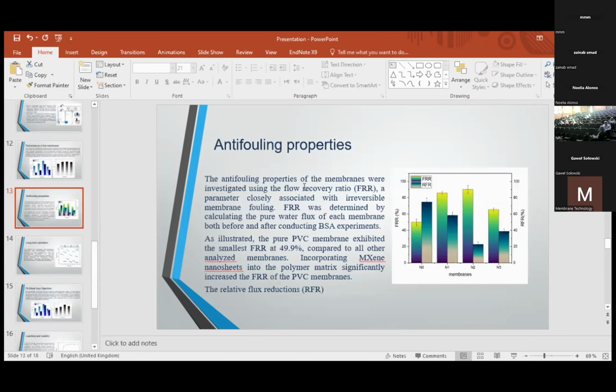For the anti-fouling properties of the membrane, we investigated using the flux recovery ratio, a parameter closely associated with the irreversible membrane fouling. FRR was determined by calculating the pure water flux of each membrane both before and after conducting BSA experiments. As illustrated, the PVC membrane exhibited the smallest FRR at 49.9% compared to all other analyzed membranes. Incorporating MXene nanosheets into the polymer matrix significantly increased the FRR of the PVC membrane and also decreased the relative flux reductions.